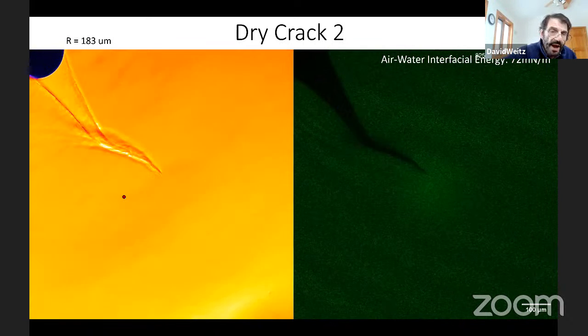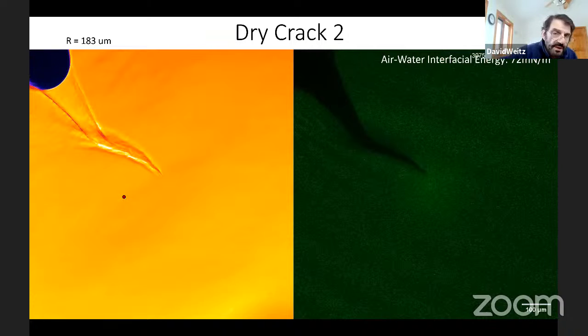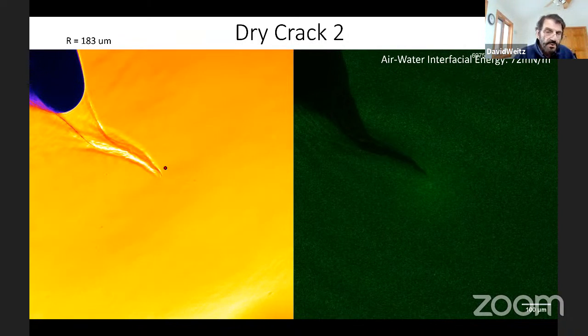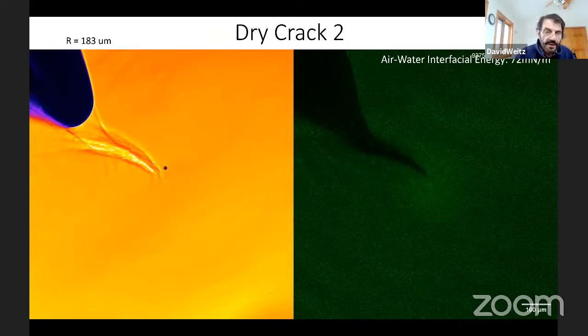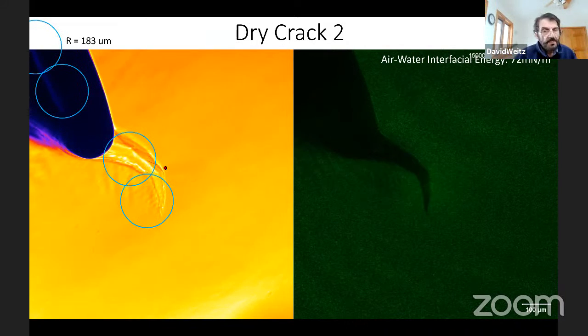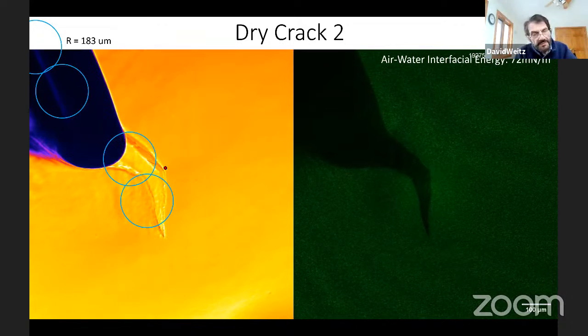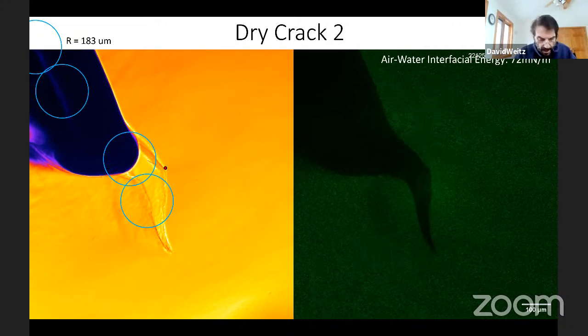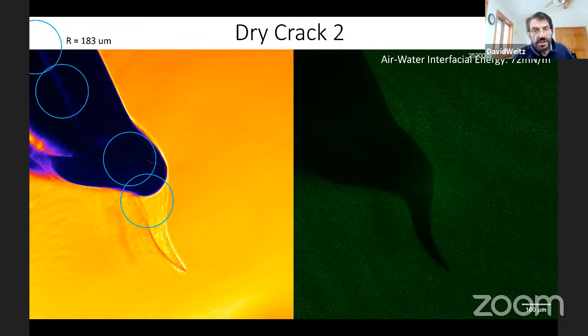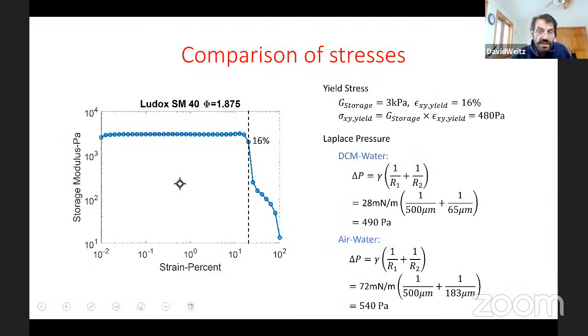Even when a crack changes directions, like this one is going to change directions and go in this direction, you see there's always water in front, and there's always the same radius of curvature. So that radius of curvature must be what's driving the crack. And so CG did some very simple calculations, and these are just order of magnitude calculations. He went to the rheometer, he made the same sample, he measured the yield stress, and for this sample, it's about 500 pascals, a half a kilopascal.